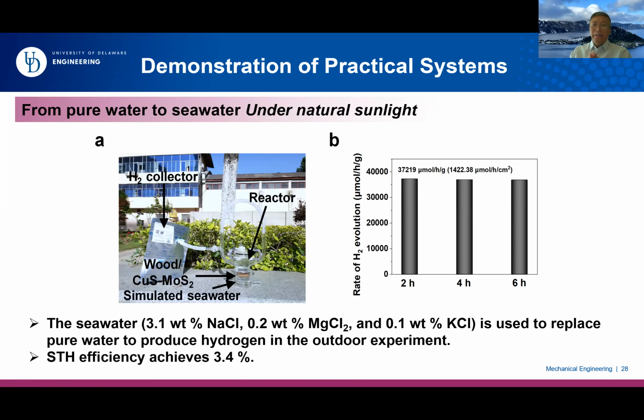So we also tried going from pure water to seawater and using natural sunlight, as shown here. This is a quite simple demonstration, and we apply here the copper sulfide, molybdenum disulfide, and use simulated seawater, about 3% salt, and we can achieve solar to hydrogen efficiency of about 3.4%, and also very, very stable. We measured 2 hours, 4 hours, 6 hours of hydrogen production, and they are pretty much the same.